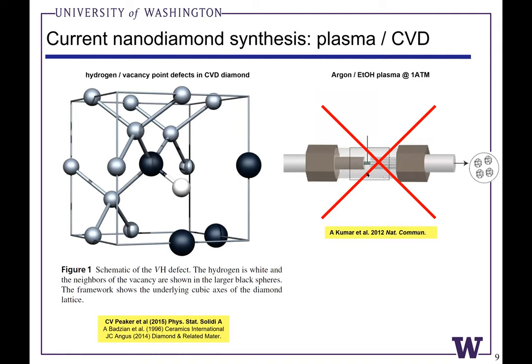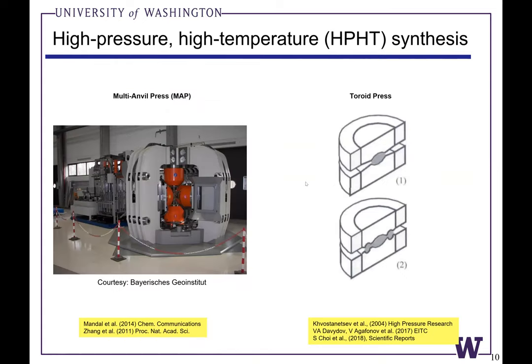There are some recent reports of using atmospheric pressure plasmas to grow nanodiamonds in Nature Communications. Our group has tried to reproduce these papers and we've not succeeded so far, but there are some really nice ideas for how you could potentially nucleate and grow diamonds in near atmospheric pressure conditions. I also wanted to discuss briefly some very nice work using multi-anvil press apparatus experiments to grow relatively large amounts of diamond material using well-defined temperatures and pressures.